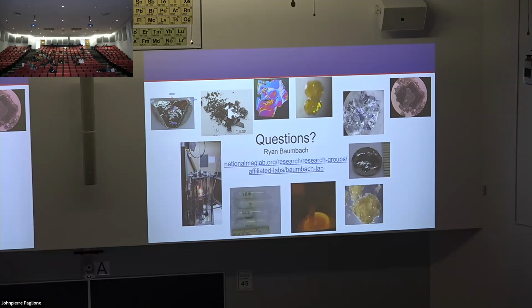There's differences in the way that convection works in the melt zone too, right? Because in the optical float zone, you're creating a melt zone, but any convection is going to be due to your ambient conditions, right? You're in gravity. There's cold, hot, cold. Those sorts of things are going to change the way that convection works. And in fact, that convection really does impact the crystal growth. In an induction furnace, there's a magnetic field that's breaking the axial symmetry, and that changes the way that the melt does its convection. I don't know anything quantitative about those things, but I think that's what you would think about.